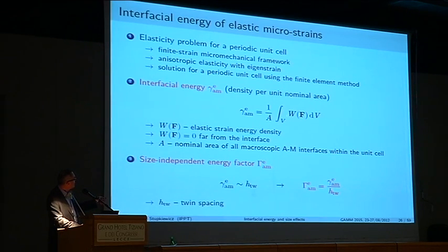We can integrate the elastic strain energy, assuming that it's zero far from the interface. We apply such conditions that this condition is fulfilled. If it was not, we would have to subtract the far field fields, but this can be done also. And then we relate this energy to the area of the nominal interfaces we have in our unit cell. That's it. So we have the interfacial energy.